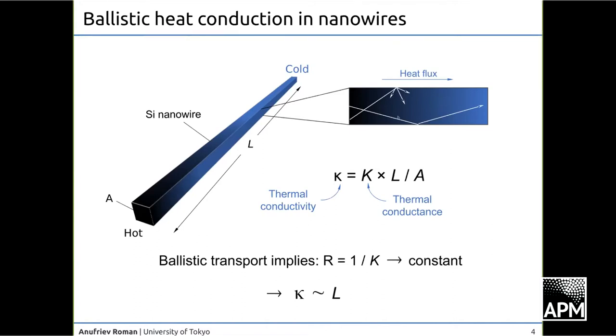In this case, we have a reduced resistance of such a structure. And particularly in the ideal case, where all phonons experience no resistance, the resistance goes to a constant. In this case, the formula simply collapses to thermal conductivity proportional to the length. And that's how we can probe in the experiment that we have some kind of ballistic contribution. Of course, it's never ideally proportional to L, but it can be L to the power alpha, as introduced by Professor Chen. Yes, so this is how we aim to probe ballistic heat conduction.